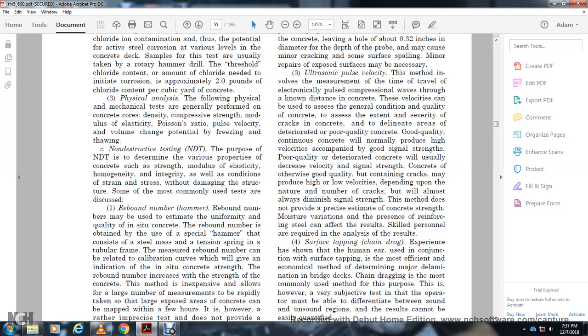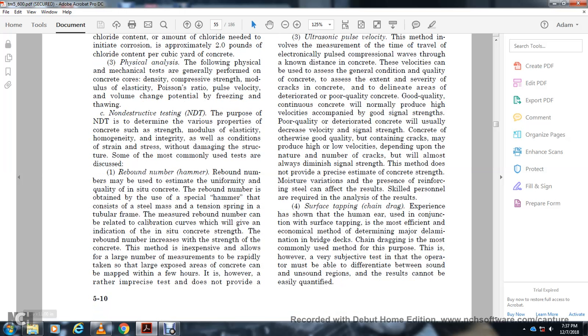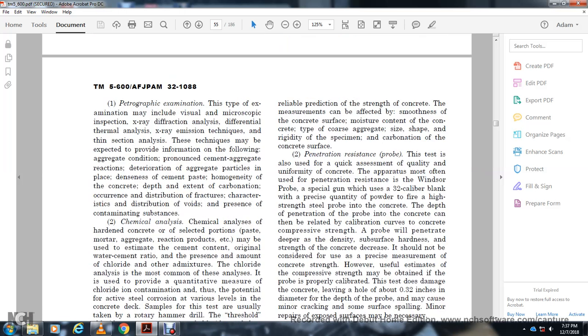The rebound number increases with the strength of the concrete. The method allows a large number of measurements to be rapidly taken over large exposed areas of concrete, which can be mapped within a few hours. However, the rather imprecise method does not provide a reliable prediction of the strength of the concrete, and the result can be affected by the smoothness of the concrete surface,